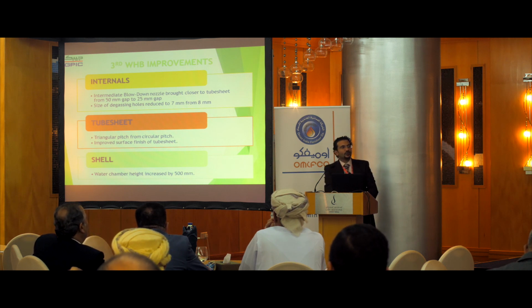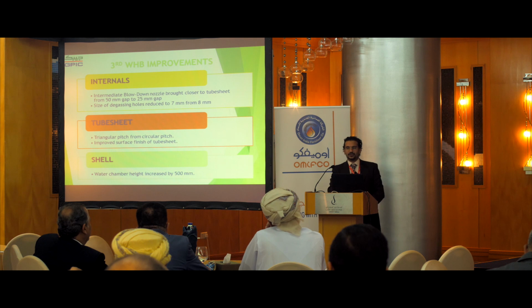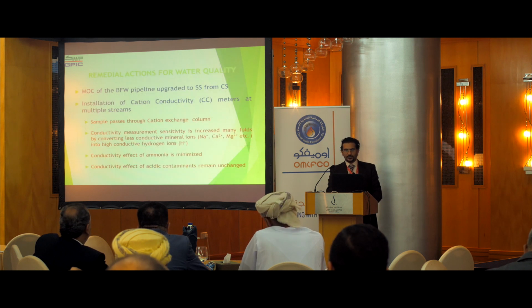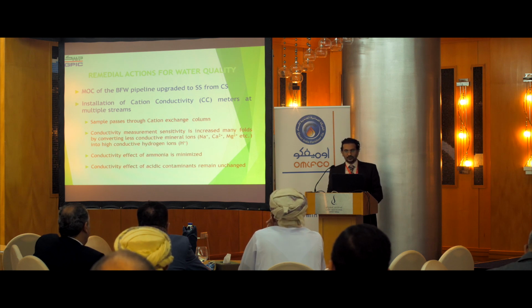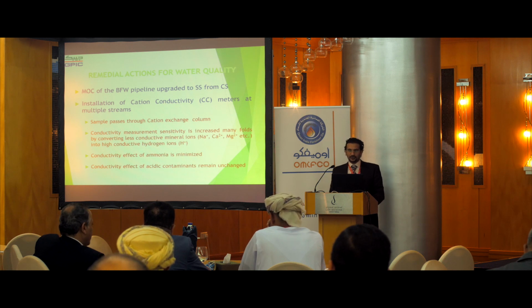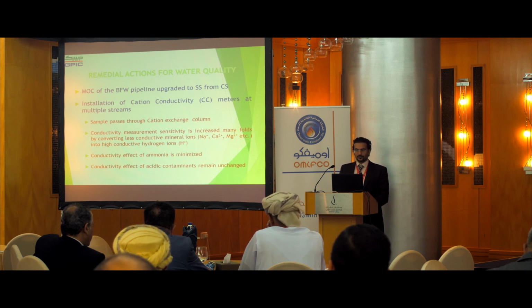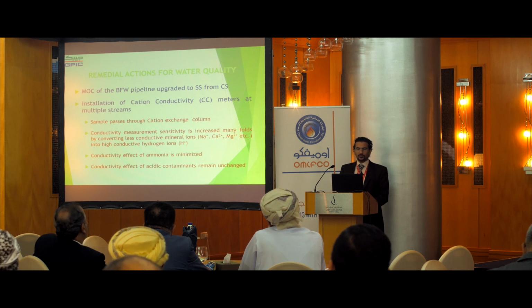And for the shell, the water chamber height was increased by 500 millimeters. For the water quality, the boiler feed water pipeline was upgraded to stainless steel from carbon steel. And we installed cation conductivity meters in multiple streams to have close monitoring of the conductivity and the pH of the water and the steam.